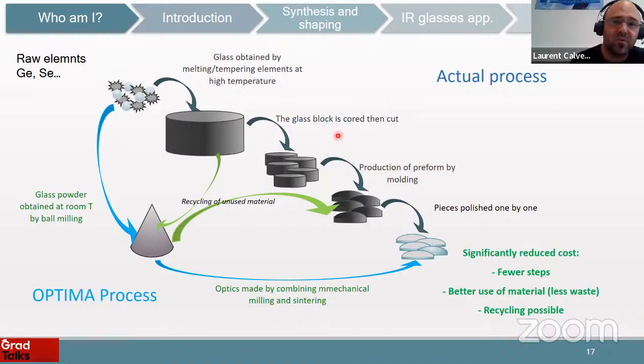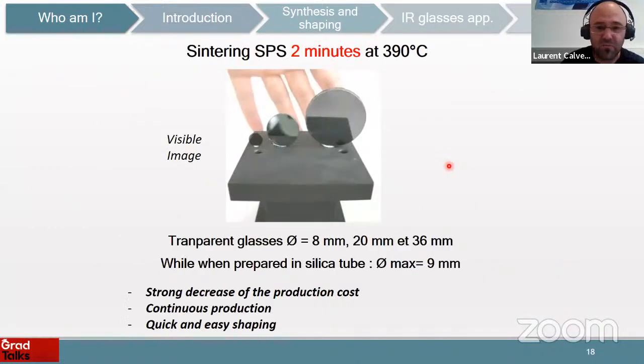As I told you, the actual process needs melting and quenching of elements, and then you have to core the bulk, to cut it, to polish it. And so it's a long process. You lose a lot of matter, and using our Optima process, just by grinding, you can obtain your amorphous powder, and by sintering, you will directly get the lenses. So fewer steps, better use of materials, and what is very interesting is that here you can recycle all of the materials. So I've been contacted by a lot of companies who wanted to use this process.